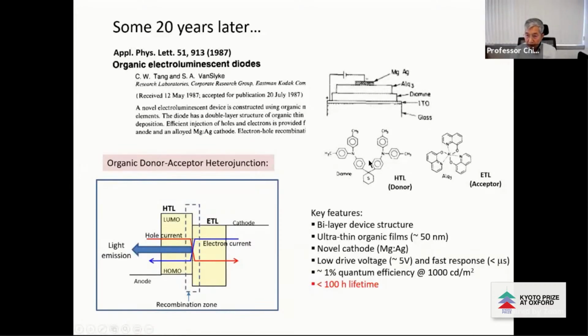With these two, the donor and acceptor, having a bilayer structure, again using ultra-thin organic films, roughly about 50 nanometers each, and coupling that with a novel cathode at the time called the magnesium silver alloy, you get a drive voltage of about 5 volts and a very fast response time on the order of microseconds. And we get a quantum yield of just about 1%, just like the paper in the 60s. But we get pretty high brightness. And the problem we had at the time was that the lifetime is relatively short, about 100 hours.